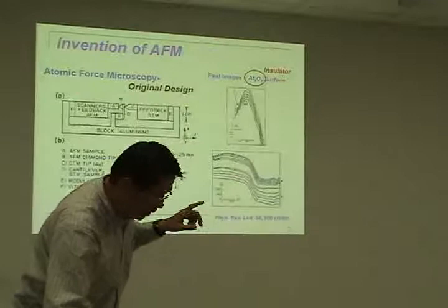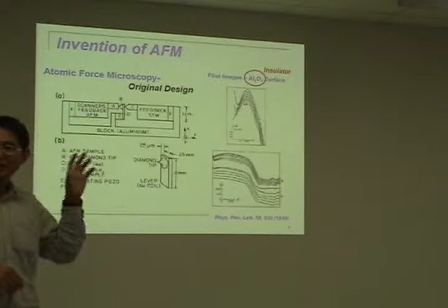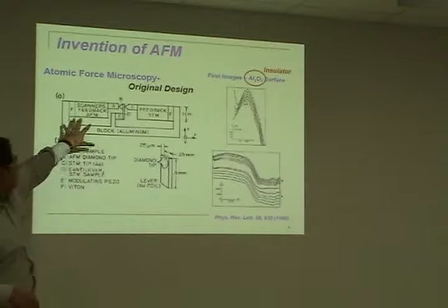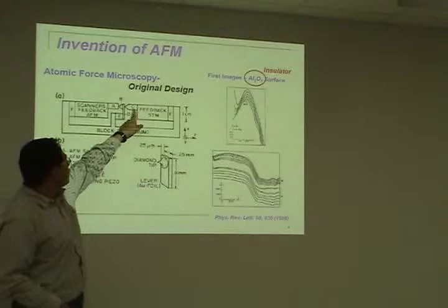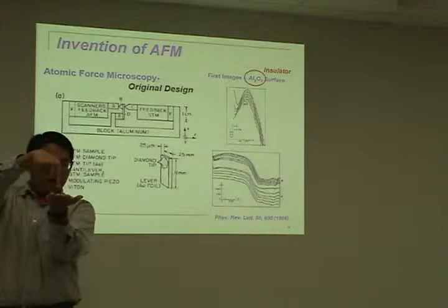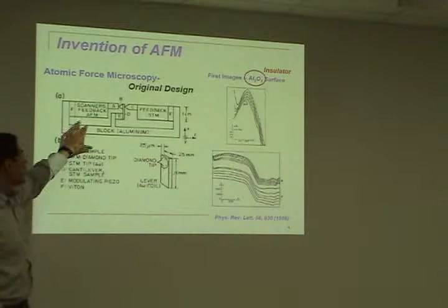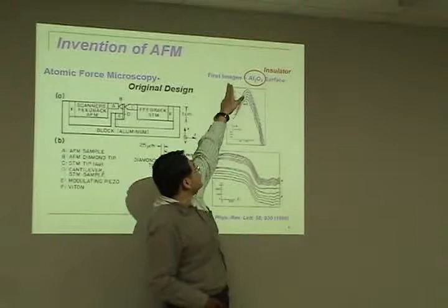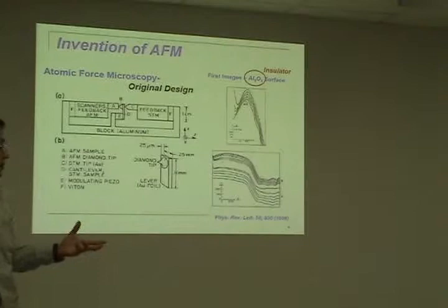That led to the invention of AFM. The same people who won the Nobel Prize knew the limitations of STM, so in 1986 one of them invented atomic force microscopy. The basic idea is similar: here is the sample and here is the tip. But for AFM the tip nominally contacts the surface and measures the surface profile. The big achievement is that the first image was scanned on aluminum oxide, which is insulating — so it breaks through the limitation of STM.